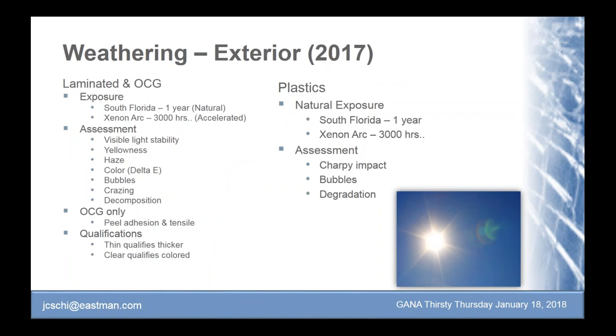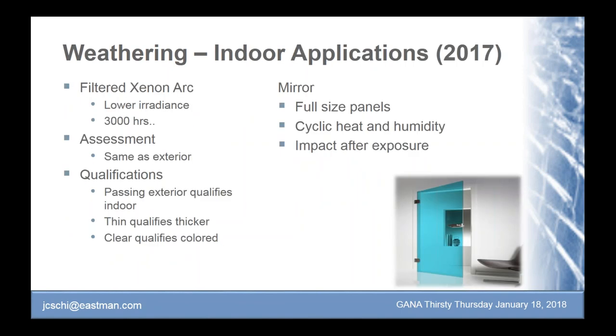The weathering at the exterior, this is a part that has changed a bit. This is all incorporated. It was not in the 1990 version. So you can do, as I said, South Florida or accelerated. You do an assessment on the products for polymer degradation. And some qualification things are that thin product qualifies thicker product, and clear products qualify colored products. So that is in there as well. Indoor applications are essentially the same exact weathering requirements, but through a filter that simulates the sunlight coming in through the glass before it hits the product. So it's got a second level of filtering, if you will. And it has to pass those requirements and has the same qualifications.